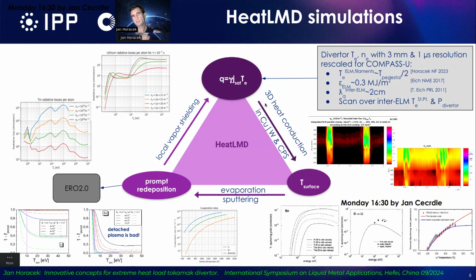And then this determines the surface temperature, and this determines the evaporation and sputtering according to these well-known rules, which are described in my last paper, Nuclear Fusion. And then what is sputtered and evaporated is partially put immediately back thanks to prompt redeposition. This is especially true for tin. So most of the particles of tin go immediately back to the surface within 1 Larmor radius, but only at high temperatures, so above 10 electron volts. So for detached plasma, which has very low temperatures, this unfortunately doesn't work.